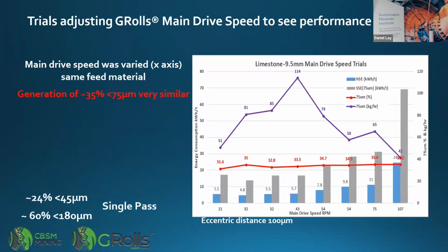One thing we did was we looked at the different configurations of the unit and how they impact the performance. We changed the main drive speed, and this was quite an interesting chart. Remember, the main drive pulls material into the unit, and so that speed is changed. When we had really high speeds, we were generating much higher energy consumption, but also lower productivity for those high speeds.